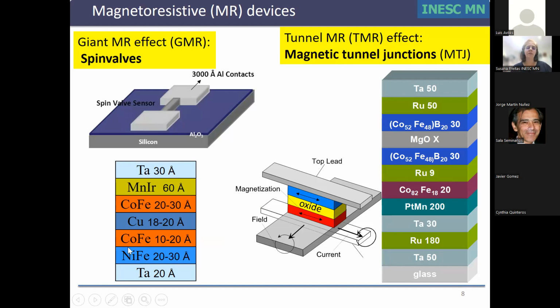And the structure of these spin valves is comprised of, you should always look here, the copper spacer, one to two nanometers thick. And then on either side of the spacer, we have a ferromagnetic film. And then we may have complicated structures below and after that are required and are engineered in order to have a good control of the grain size, the structural interfaces, the temperature stability, etc. So I'm not going to go into too much detail here. I just have to show this as an example.